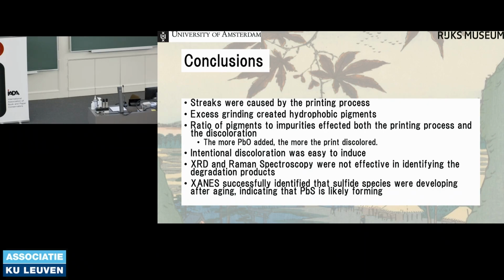So some quick conclusions. I found that one of the patterns observed in the discolorations that I observed at the very beginning was in fact probably a byproduct of the printing process, while the other one observed, the haloing, could not be recreated and the cause could not be determined. I found that the thickness of the paper did not affect the printing process or discoloration of the prints, at least at this scale. The grind of the pigments significantly affected the printing process, with too much grinding making the pigments hydrophobic and potentially causing printing errors. The ratio of pigments was by far the most important element, with increasing amounts of impurities causing less consistent prints, prints that discolored more rapidly, more completely, and more readily turned to silver. Intentional discoloration was found to be very easy to induce, though it could not be proven that it was performed.